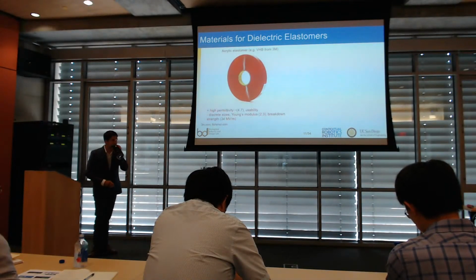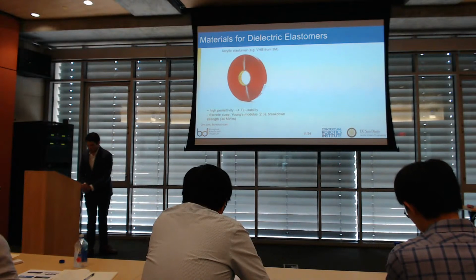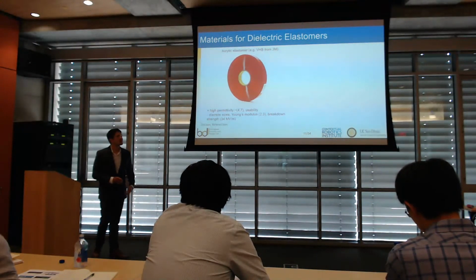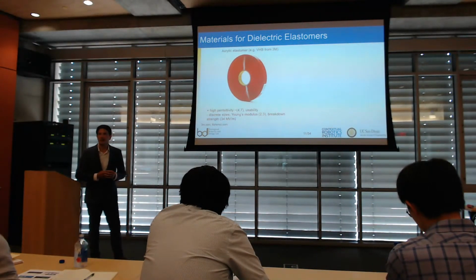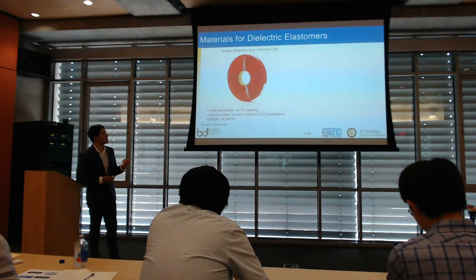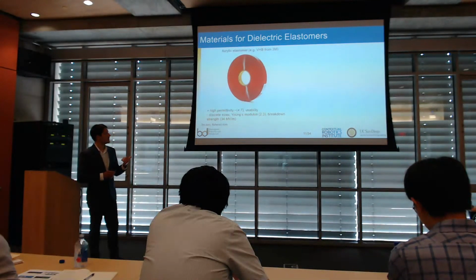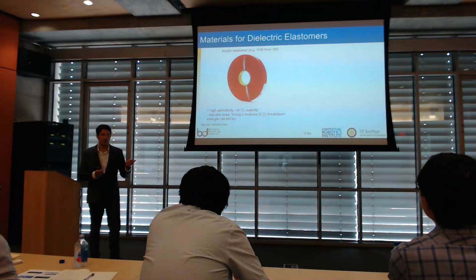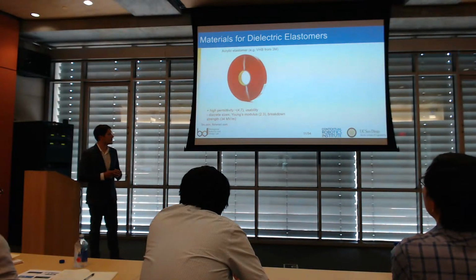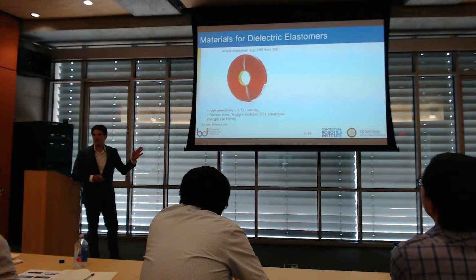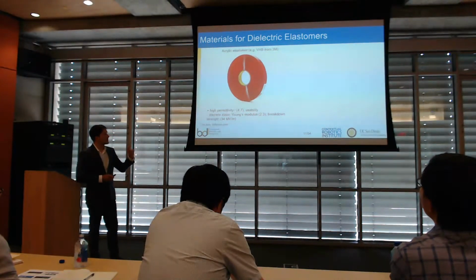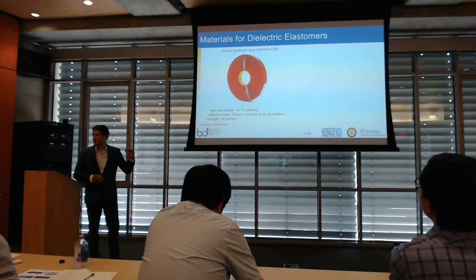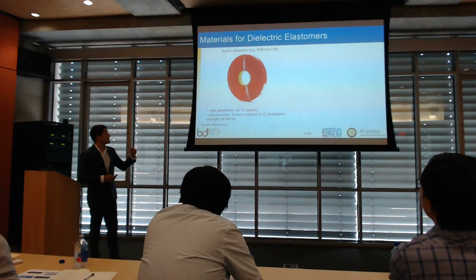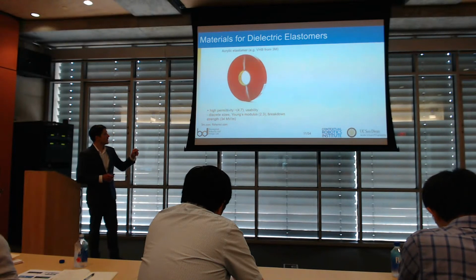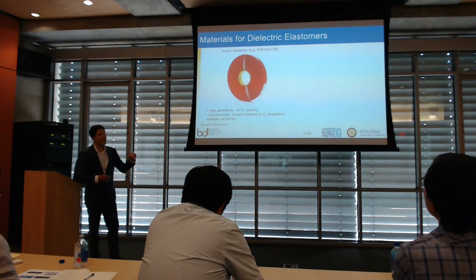So the two materials that people normally use for DEAs, one is an acrylic-based elastomer. A very popular choice is VHB. It has a high permittivity. It's also very easy to use, so it comes on a roll. I've got some examples of it over there. But the challenge with this material, even though it's widely used, is that it comes in only discrete sizes, so you can only get it at a few different thicknesses. It has a high relative Young's modulus and a low breakdown strength.